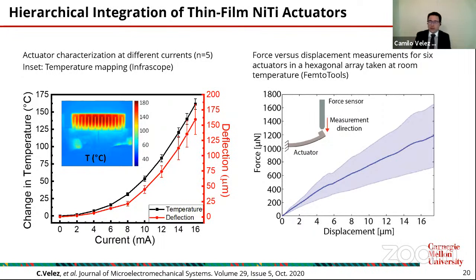Now, for lower temperatures, the actuator can also work at lower temperatures, but the current is going to heat it up. This is a thermal actuator, so we need to heat up the polymer below 100 Celsius, and heat up the nickel titanium, the shape memory alloy, above 100 Celsius to get a phase transformation. So the current needs to pass and heat up the material, otherwise you're not going to experience any actuation.